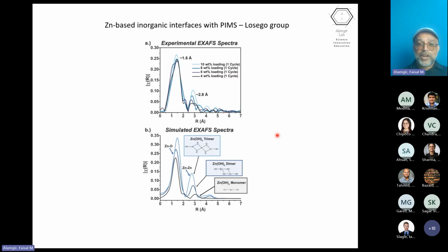So this kind of analysis is possible. This is now, I'm showing quickly some data from the Losego group. This is work in collaboration with us. They are interested in these so-called polymers with intrinsic microporosity that can be hosts for inorganic particles to adhere to them, to interface with them. So they use a very special technique called vapor infiltration, by which they are doing something akin to ALD, but the ALD is now of inorganic materials onto organic surfaces, internal organic surfaces.